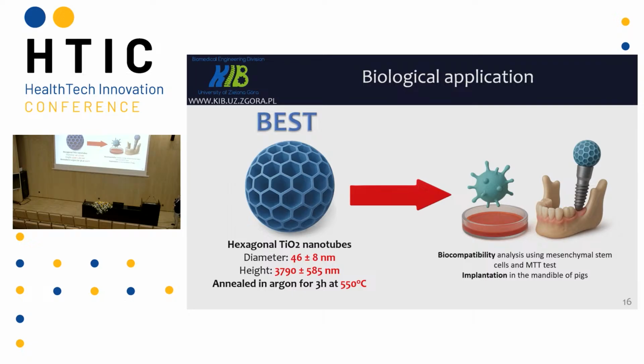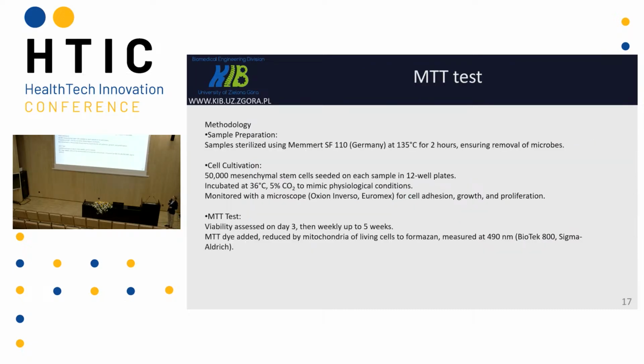And the next step was the biocompatibility test using a simple MTT test and the implantation into the mandible of pigs. So we sterilized our samples. The diameter of the HTNT was 50 nanometers. The length was 3.5 micrometers. We annealed it in argon atmosphere for 3 hours at 550 degrees Celsius.